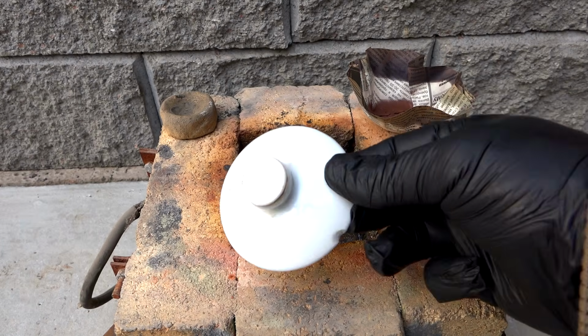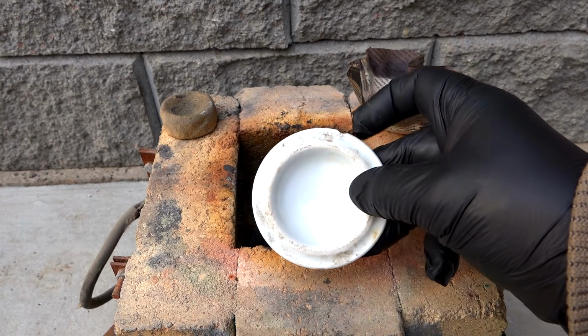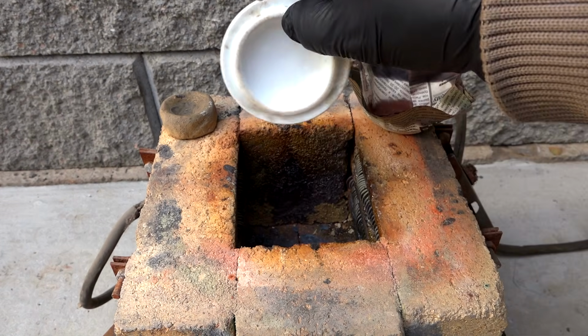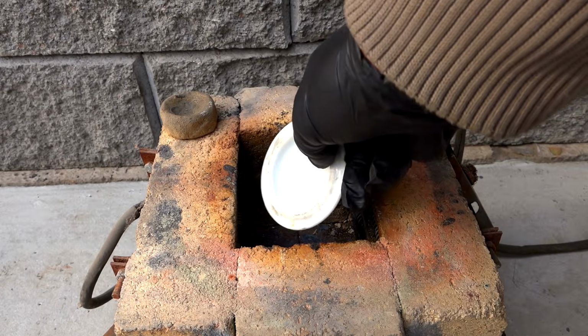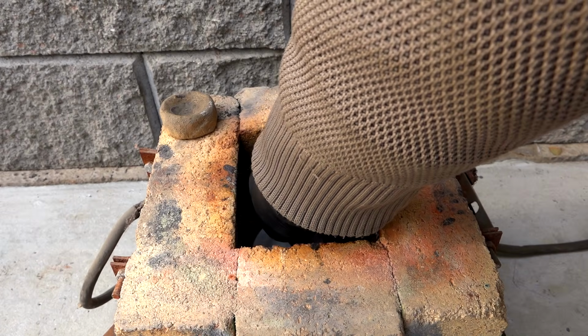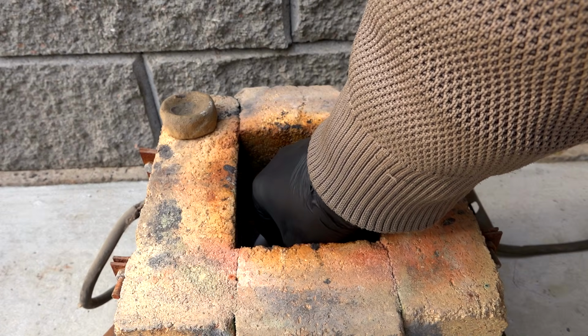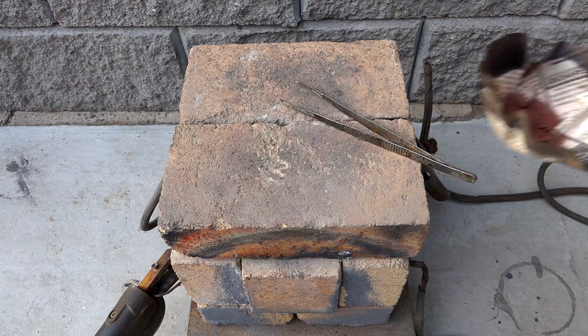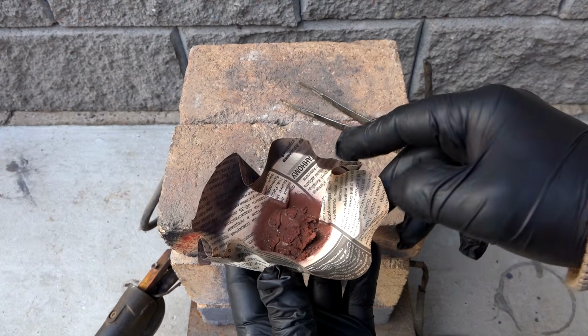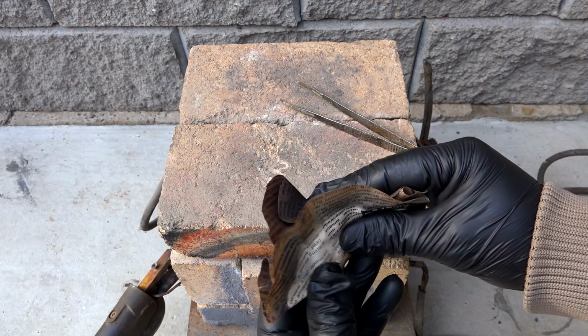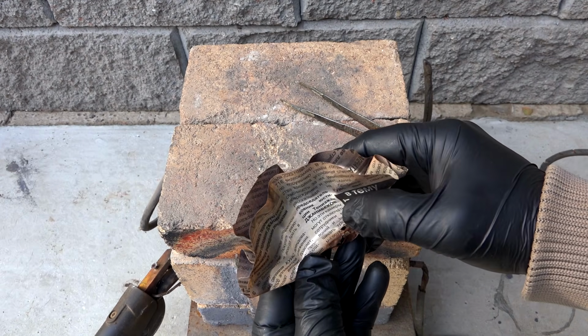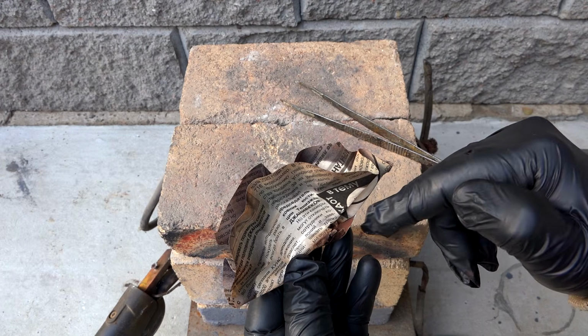I will melt the precipitate with gold in a muffle furnace, and in place of a crucible I will use a ceramic lid from some kind of dishes. I carefully put it in the muffle furnace, add a little borax, and turn on the heat for 20 minutes. After 20 minutes, the muffle furnace was heated to a temperature of 600 to 800 degrees.